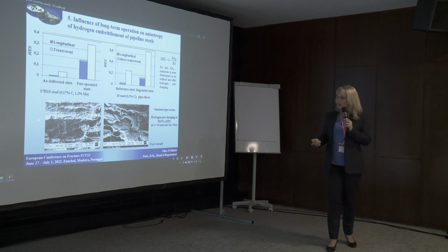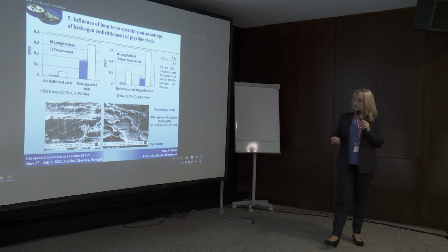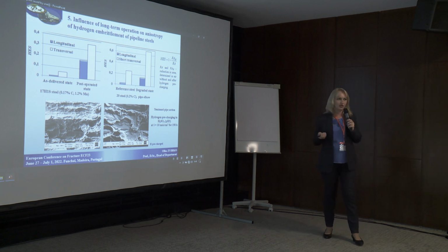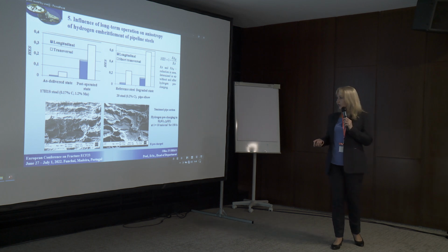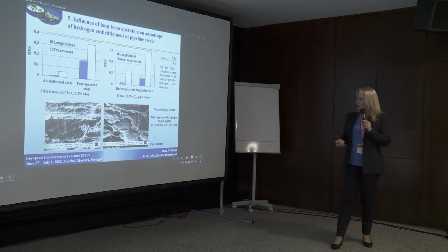And here I presented fracture surfaces of specimens made of the tension section of a pipe elbow and tested without hydrogenation and after preliminary hydrogen charging. We can observe a ductile fracture mode for the non-hydrogenated specimen and also features of embrittlement due to hydrogenation for specimens after hydrogen precharging: delaminations originated from non-metallic inclusions and propagating along the rolling direction, and also brittle transgranular cleavage.